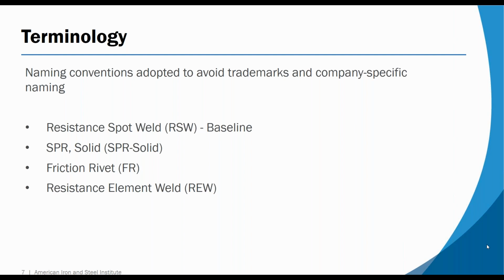The second technology is a friction rivet, which is a rotary process that spins up a steel joining element to enough speed and temperature that it's able to plasticize the top aluminum layer, push the aluminum out of the way, and then friction weld to the second layer. Because this is a friction weld and essentially a surface solid state joint, it only works on 2 thickness joints, which you'll see in the later tables.